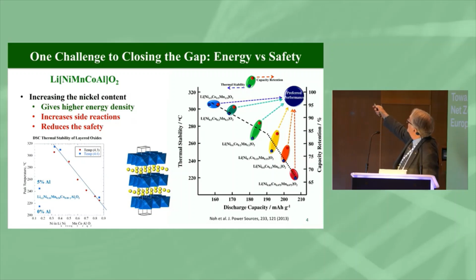If we want to make it safer, then it's this lower nickel content, lower energy density. So we're trying to push over here. We want to get the safety and infinite lifetime. Our batteries hopefully are never going to operate at those temperatures, but that temperature is a direct measure of how reactive these materials are with the other cell components, particularly the electrolyte. And I've just plotted the same sort of data here, some of our data. The only parameter that matters for this evolution of oxygen is the nickel content. The degree you charge it to or anything else you put in there doesn't have much effect. So it's totally the nickel content. We need to be aware of that as we push forward.